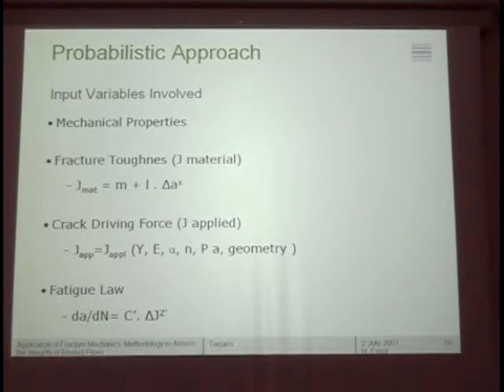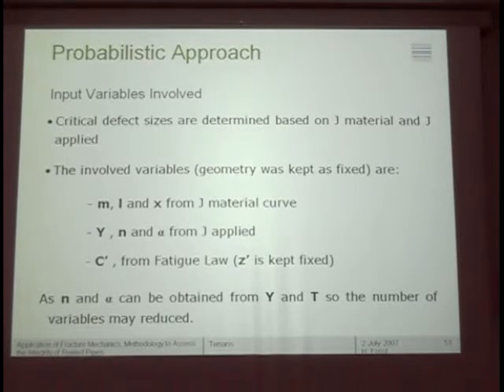fatigue law, 2 constants. So here, the input variables for the statistical model, as I said, are the J, m, l, and x from the J material curve, the 3 for the tensile behavior of the material, the parameters Y, n, and alpha, and we are taking as an example C prime, which is the constant from the fatigue law. We are keeping the exponent fixed. There are some equations that connect the Ramberg-Osgood exponent and alpha with the Y and T, that is the ultimate, which is typically what you get from the mill.